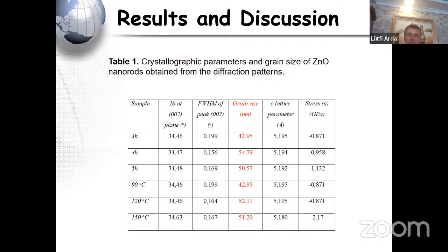Moreover, the 002 peaks of the samples shifted toward higher 2 theta angles as the temperature and the growth time increase in the crystal structure. The compressive stress occurring in the direction parallel to the surface may affect the lattice properties in the direction perpendicular to the surface, which appears with the shifting of diffraction peaks.